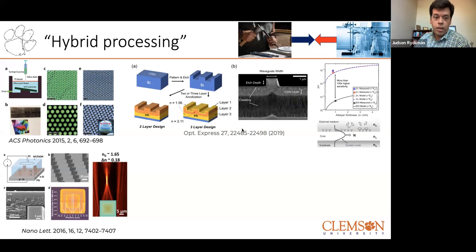So this is work out of my group. We've taken a similar idea to what Paul Braun has done here. We first pattern silicon, so we go ahead and do conventional photolithography and etching just to make this rib structure. But then we go in and we anodize the sample in our etch cell, and we do it in 2 or 3 layers. So first we etch a low porosity layer, and because it has a higher fraction of silicon, a lower fraction of air, it has a higher refractive index. But then we continue the etching and increase the current density, and that allows us to increase the porosity. So now suddenly we can make a high refractive index, low refractive index structure.